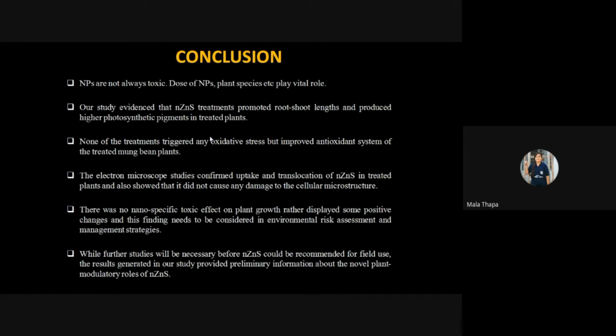Now, nanoparticles are not always toxic. Dose of nanoparticle, plant species, etc. play a vital role in the toxicity. In our study, zinc sulfide nanoparticle treatment promoted root and shoot length and produced higher photosynthetic pigment in treated plants. None of the treatments triggered any kind of oxidative stress but improved the antioxidant system of the treated plants.